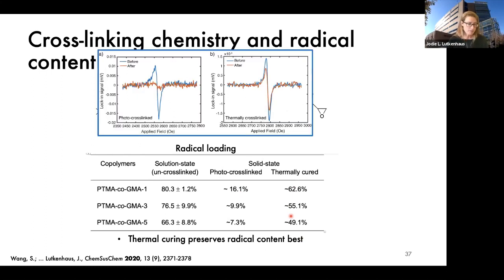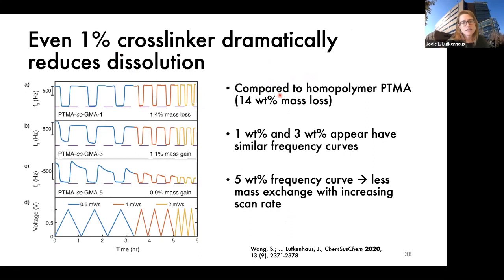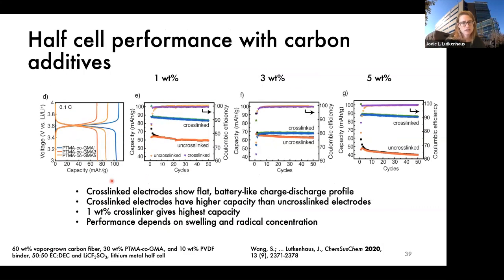You can see that in these EPR curves, where with photo cross-linking, you pretty much lose the signal, and with thermal cross-linking, the signal diminishes, but it still persists. This is EQCM-D of the cross-linked PTMA, and with all of these compositions, whether it's 1, 3, or 5 weight percent glycidyl methacrylate, we have very little mass loss. In some cases, we even have mass gain as we're cycling, because electrolyte is penetrating into the electrode in a process we call conditioning. Depending on what you're looking for, any of those compositions might be okay. At 1 weight percent, we have a little dissolution, but it's really not too bad.